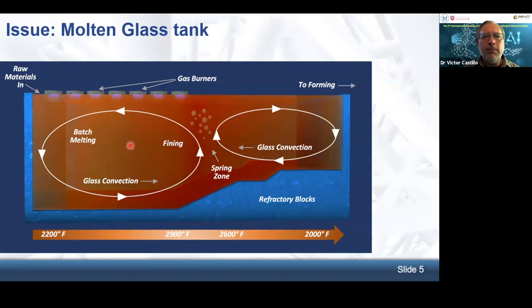So the industry has come up with a clever way of putting these burners up at the top, and the heat moves through the glass and is reflected off the bottom, off this reflective material at the bottom, this refractory brick. What this causes is an outgassing of the raw material. The outgassing causes a buoyancy, and this buoyancy causes these convective loops. These convective loops are actually producing the mechanical agitation and stirring necessary for the product to mix properly. So it's all about adjusting the heat distribution at the top, along with a few other mechanical assistance, like gates and other ways of mitigating the flow. This causes the proper mixing in the glass tank.